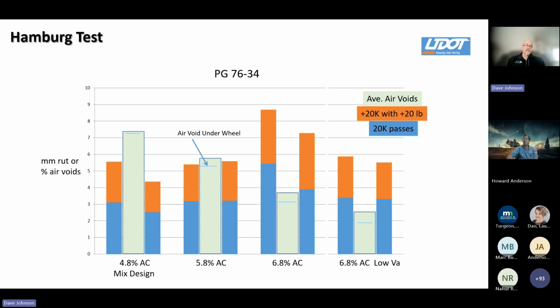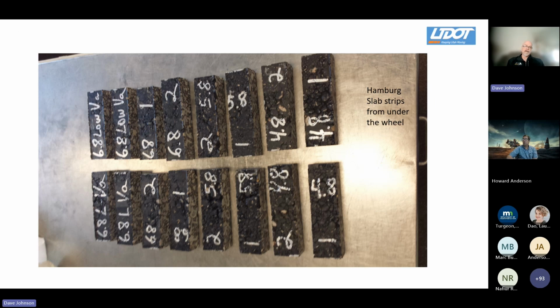The other thing to notice is 10 millimeters is the rut criteria for Utah on their typical Hamburg at 20,000 passes. Even after 40,000 passes, the worst performer was still meeting that requirement at just under 9 millimeters of rut. Here's what those slabs looked like just visually so you can see. These were cut from directly under the wheel, and so there's not a lot of distortion that we see there.